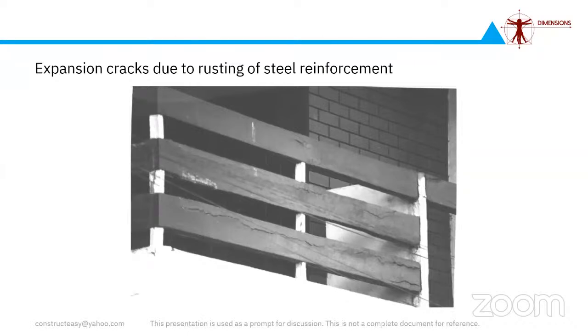But corrosion is different. This is not an oxidation reaction. Corrosion is an electrochemical reaction. So when the same member, the steel, is subject to two different environments, like of different pH, one part becomes cathodic, the other part becomes anodic. So this is the simulation of a typical electrolytic cell, where you have an anode, a cathode, and an electrolyte. This electrolyte is also simulated in a concrete system where your pore water, the pore moisture, acts as the electrolyte. You have one portion acting anodic and another portion acting cathodic. Why should this act as anodic and cathodic at different regions? It is either because it is embedded in a concrete with different pH.